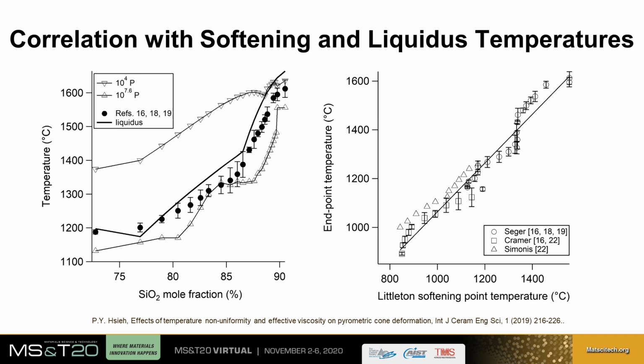A positive linear correlation was found between the Littleton softening point temperature, or the temperature at which the effective viscosity is 10 to the 7.6 poise, and the pyrometric cone endpoint temperature. The choice of the Littleton softening point is not arbitrary, as it is typically considered to be the start of the working range for glass.